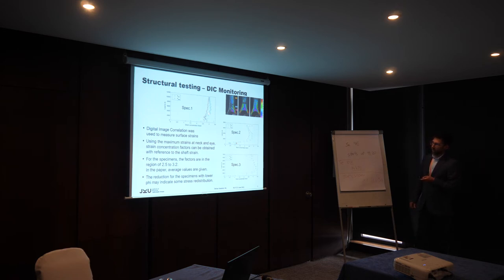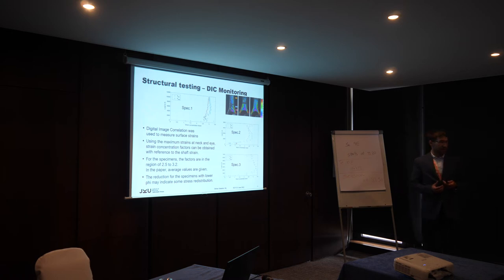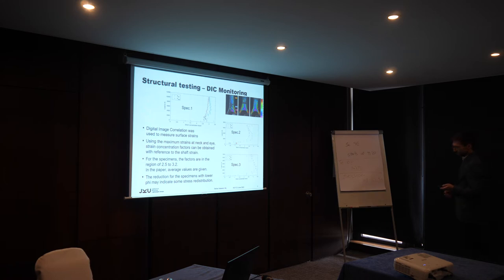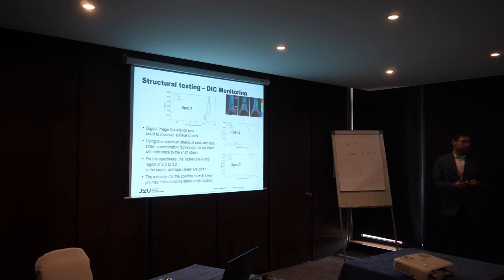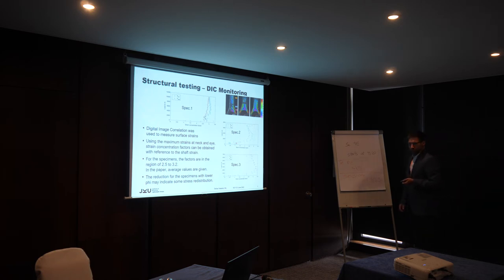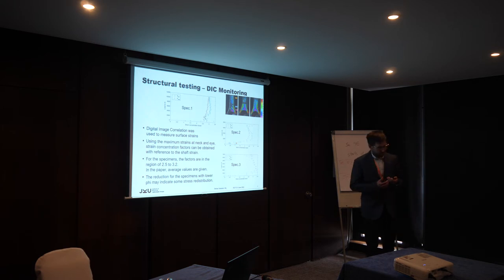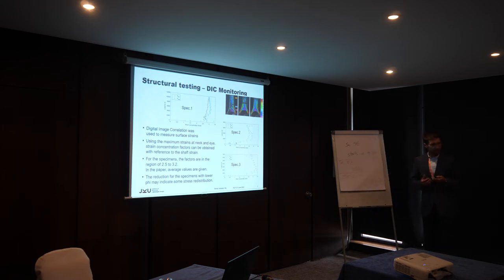So there was a secondary effect. When you reduce your fiber volume fraction and space your layers further apart, you go from a fracture mode you expect to one you wouldn't really expect. Our theory was that, since we're only measuring surface strains, there could be breakage of a layer underneath — with a low-resolution process we don't really know if any surface layer is broken.